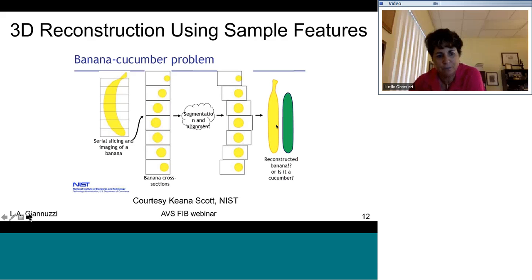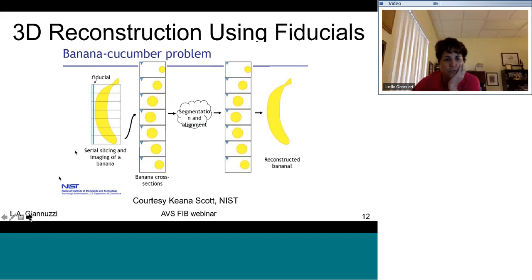Okay? So if you use a fiducial mark, this is a top-down fiducial mark, and in the slice you'll see a little piece of that fiducial mark in the image. If you use the fiducial mark to align the region of interest, then you will retain the banana shape, and you will actually reconstruct a banana instead of a cucumber. So this is why it's very important also to use fiducial marks in the 3D reconstruction.